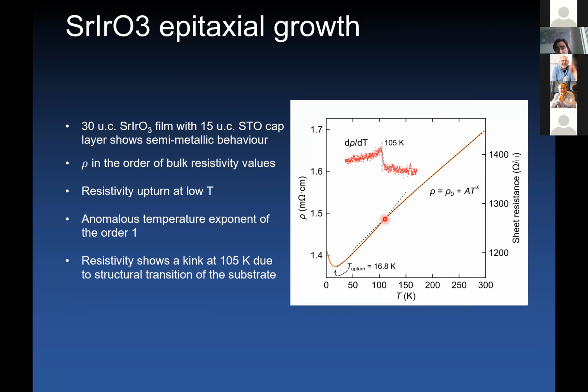And we also observe a very sharp kink in the resistivity at 105 Kelvin, where there is a transition of the crystal structure of the substrate. I will come back to this point later on in my presentation.